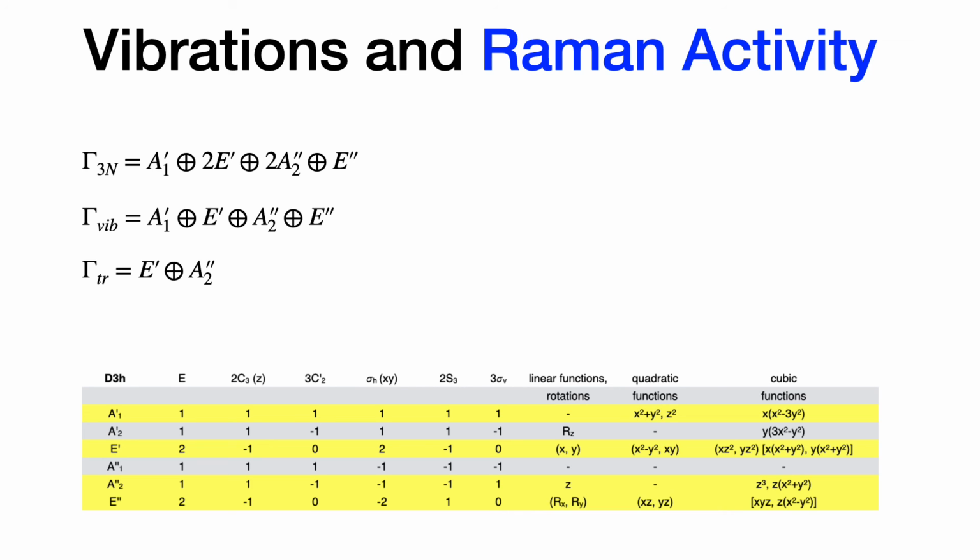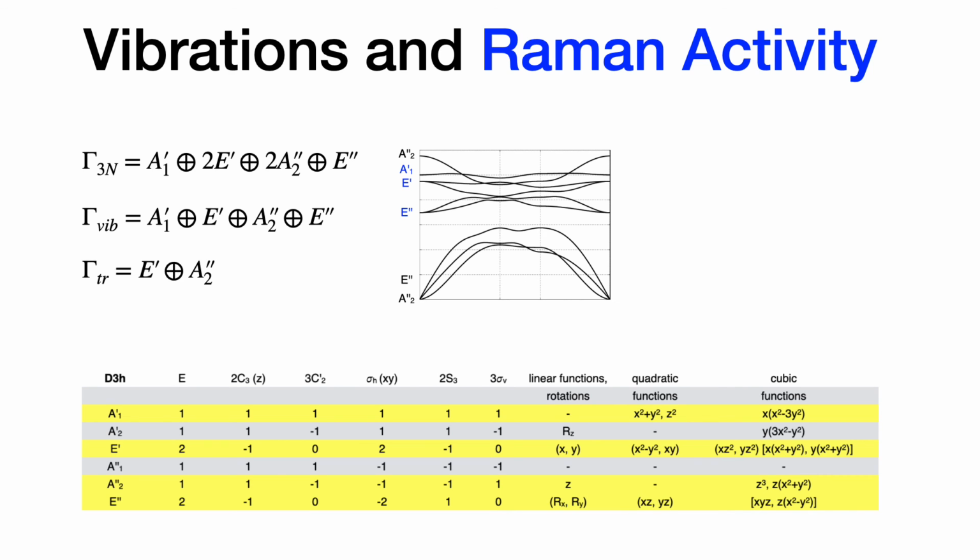And I'm going to wrap this up by showing you the phonon band structure. So this is the phonon band structure. And we can assign all the different modes, and we can see those that are doubly degenerate, like the E modes, and those that are not. In blue, I highlighted the modes that are Raman active. And we can even have a representation with ball and sticks of these guys.